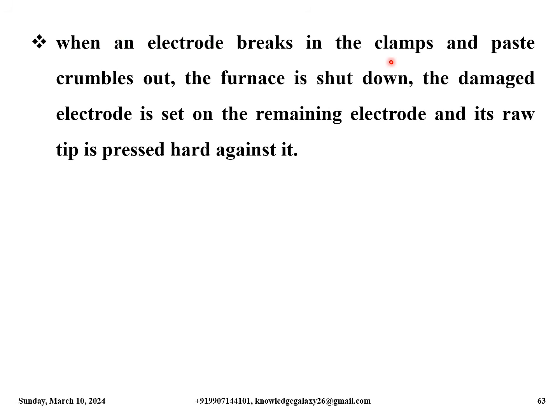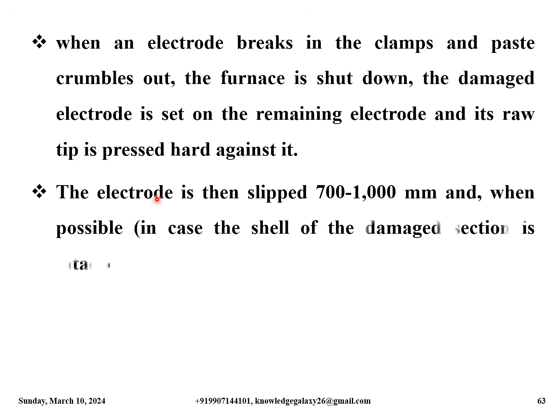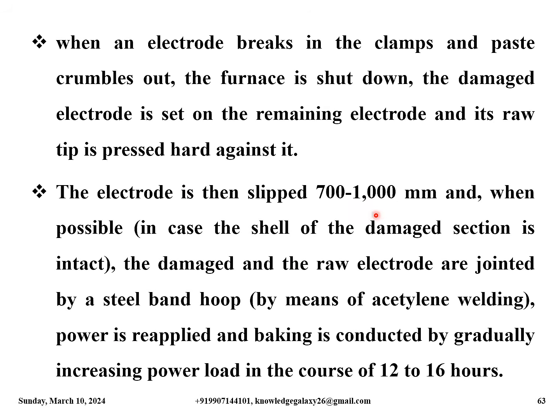When an electrode breaks in the clamps and paste crumbles out, the furnace is shut down, the damaged electrode is set on the remaining electrode and its raw tip is pressed hard against it. The electrode is then slipped 700 to 1000 mm and, when possible, in case the shell of the damaged section is intact, the damaged and the raw electrode are joined by a steel band hoop by means of acetylene welding or arc welding. Power is reapplied and baking is conducted by gradually increasing power load in the course of 12 to 16 hours.